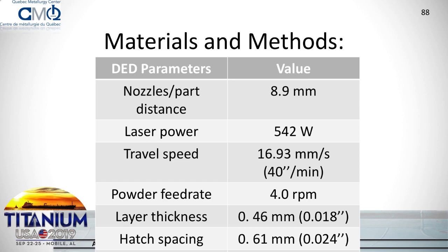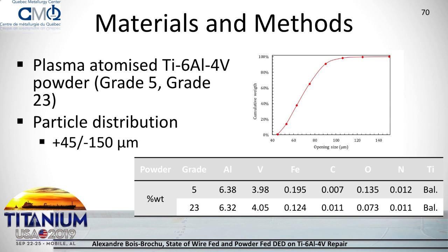So we used both plasma atomized grade 5 and grade 23 powders. The purpose is that a lot of clients have concern regarding oxygen pickup in additive manufacturing processes, and even though standards such as the AMS 4999A require you to use grade 5 feedstock, a lot of people want to use grade 23 with the objective of alleviating the concern of oxygen pickup in order to stay within the grade 5 requirements. And the particle distribution that we used is fairly standard for DED, between 45 and 150 microns.